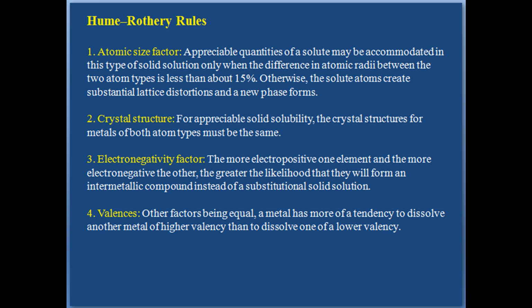Once again, we'll just repeat these Hume-Rothery rules. First is atomic size factor. Appreciable quantities of solute may be accommodated in this type of solid solution only when the difference in atomic radii between the two atom types is less than about plus or minus 15%. Otherwise, the solute atoms create substantial lattice distortions and a new phase forms.